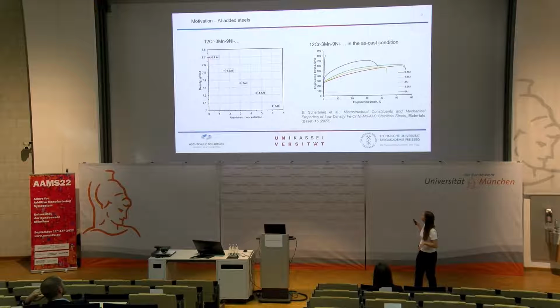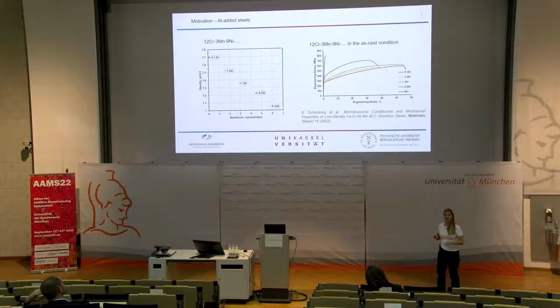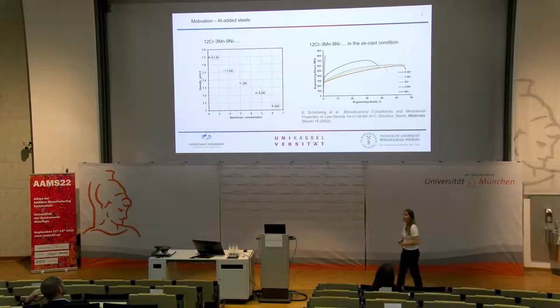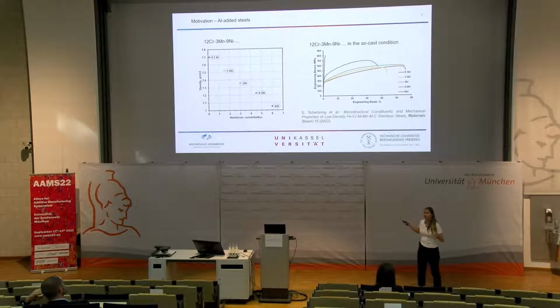increase of strength. In the as-cast condition, when we start with 0.1 aluminium, we have a 316L type alloy, with a low yield strength and a high ductility, and some work hardening behavior. But if we add more aluminium, we mostly increase the strength of our material, and in the end, up to 6%, we lose our total ductility.